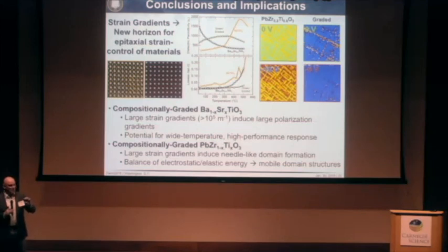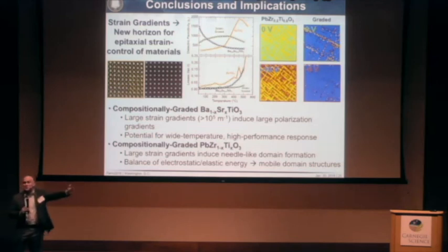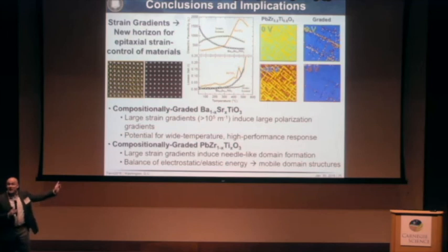So it almost behaves like the strained version of that individual composition. So it absolutely scales directly with the composition of that layer and just kind of sweeps through space across the film. But this is from MD, from your data? From the data, that's what it looks like too. From the temperature dependence, linearly depending on composition. Yeah. That's interesting. Thank you.